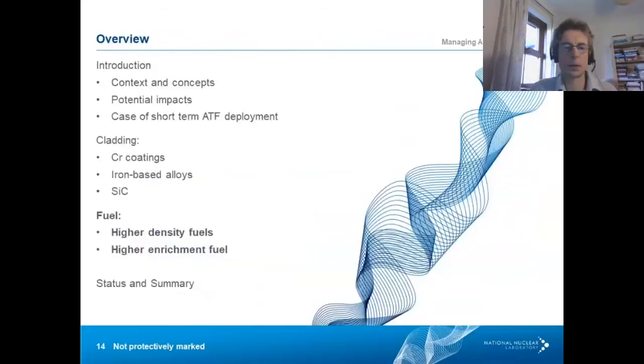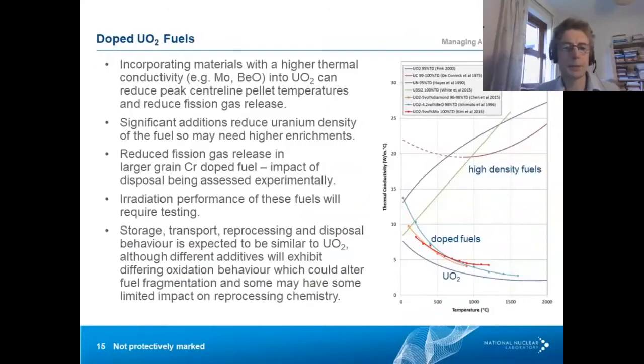Finally, I'm going to talk briefly about potential changes in the fuel itself. In terms of improving the fuel, to reduce the temperature inside the fuel during accident conditions, it's possible to dope the fuels to improve their thermal conductivity and/or to change the grain size so that fission gas release is reduced. Work was already well underway looking at chromium doping for larger grains to reduce fission gas release, and further work on that is expected to continue.